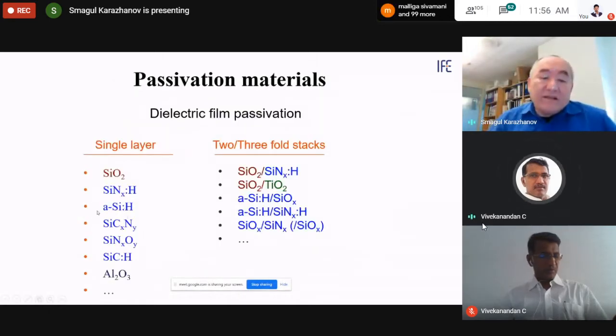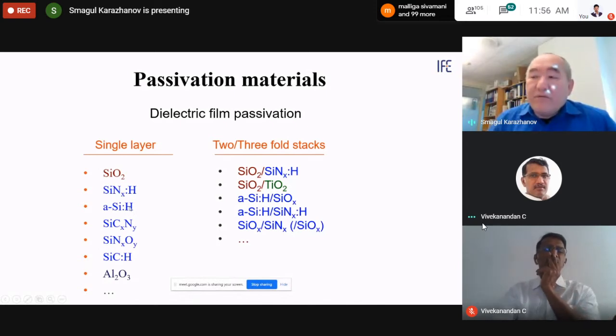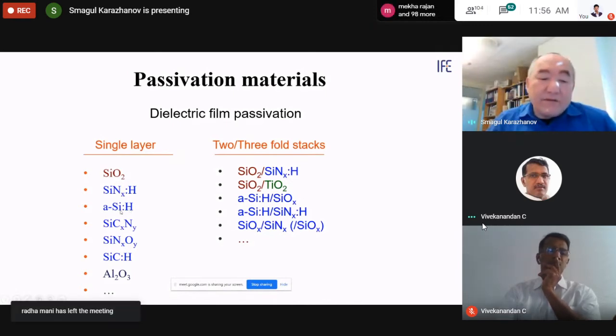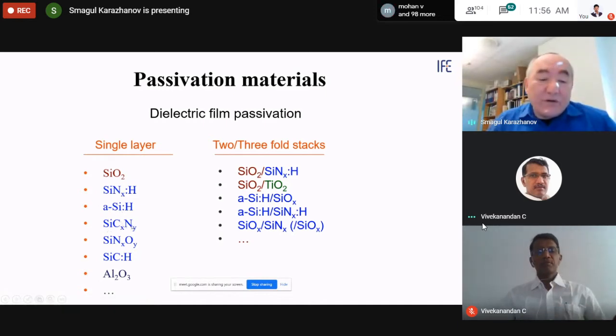Then another candidate is amorphous silicon, and you know very well, I think, this is also easy to produce. It is very unstable because of the Staebler-Wronski effect. Another candidate is silicon carbide, carbonitride, silicon oxynitride. With silicon carbide and carbonitride, passivation quality is not good enough. With silicon oxynitride, it is good, it passivates very well. However, compared to silicon nitride, it degrades very fast itself.